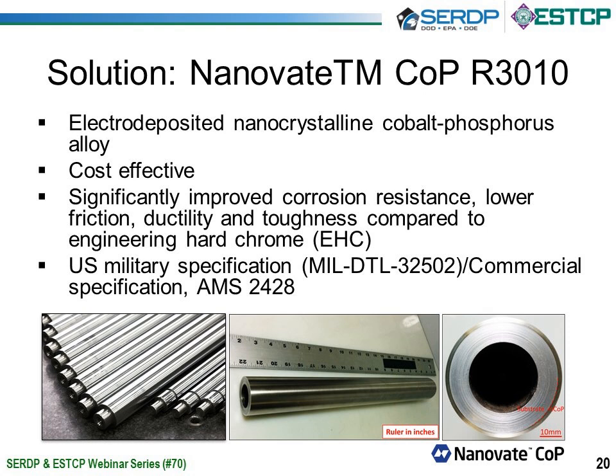So after many iterations and looking at a number of different materials, we settled on a cobalt phosphorus alloy composition as the preferred solution as an alternative for hard chrome. The nano cobalt phosphorus is simply an electrodeposited nanocrystalline cobalt phosphorus alloy. It's primarily cobalt with about 1 to 2% phosphorus, and it's electrodeposited with a grain size between 10 and 20 nanometers. It's a cost-effective process, and similarly to chrome, it's done through electrodeposition, and it provides significantly improved corrosion resistance, lower friction, better ductility and toughness compared to electrolytic hard chrome. And there's now a military specification as well as an AMS specification for the process.